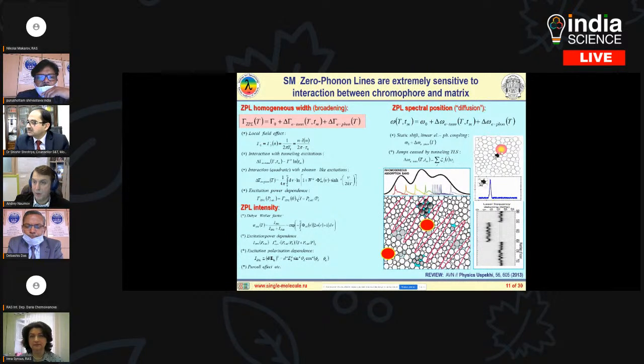For example, here you can see the interaction of a single molecule with a tunneling transition in the local surrounding. You see that we can even visualize a single quantum effect. We can investigate it not only in theory now, but also test it in experiment, because if we have such a tunneling system close to our dye molecule, and we repeatedly measure the luminescence spectrum of such a molecule, we will see such a tunneling transition as jumps of our spectrum. Then we can visualize this luminescence trail, the spectral trail in time, and we can see these jumps, and we can directly sense this quantum transition.